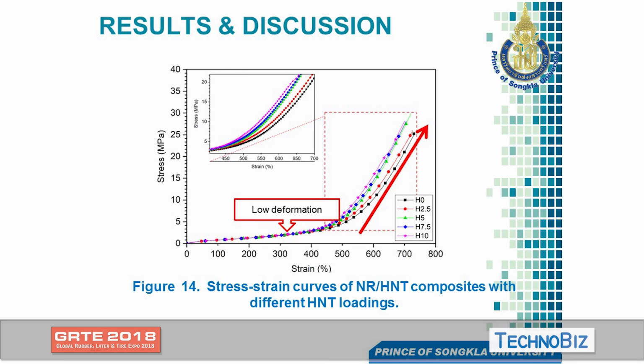Here is the stress-strain curve. As we can see, at low deformation nothing happened. The modulus increases, but only with small changes. At high deformation, there is strain-induced crystallization. Once we include more HNT, the stress increases with the addition of HNT, but this only happens at high deformation. Afterwards, I'll make a relationship with the crystallization characteristics of natural rubber filled with HNT.